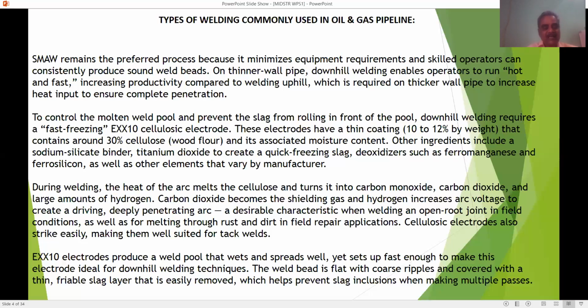During welding, the heat of the arc melts the cellulose and turns it into carbon monoxide, carbon dioxide, and large amounts of hydrogen. Carbon dioxide becomes the shielding gas and hydrogen increases arc voltage to create a driving, deeply penetrating arc. A desirable characteristic when welding an open root joint in field conditions, as well as for melting through rust and dirt in field repair applications. Cellulose electrodes also strike easily, making them well suited for tack welds.